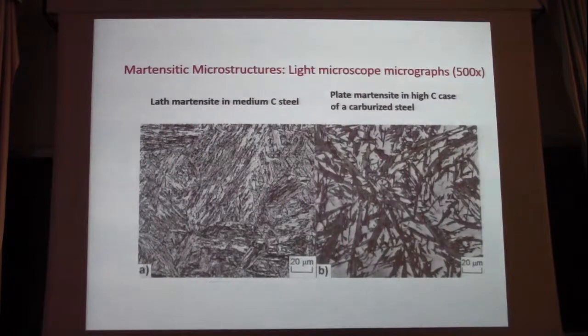Now, here are the microstructures. This is what you would see at 500X. Here is what is referred to as lath martensite. You can see that the crystals are parallel to one another in packets or blocks, basically. And it's fuzzy. And why is it fuzzy? Because the light microscope cannot resolve the finest crystal structures of the martensite. So you can see some of the crystals in the martensite, being hardened steel, but the structure is so fine, light microscopy cannot resolve all of the finest crystals of martensite.